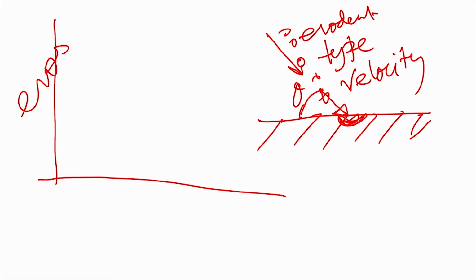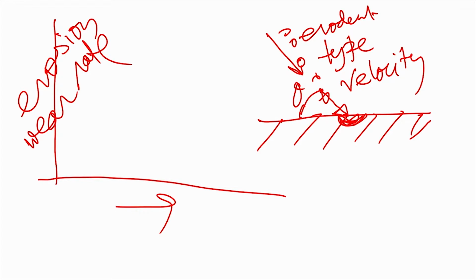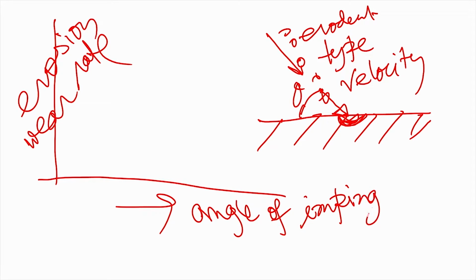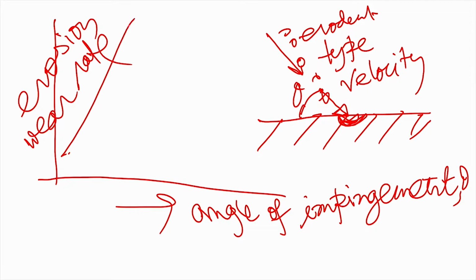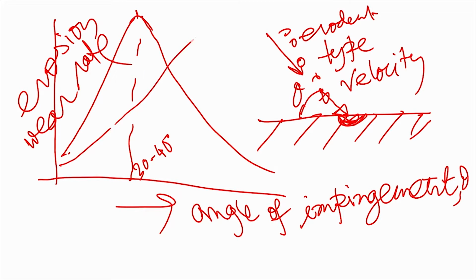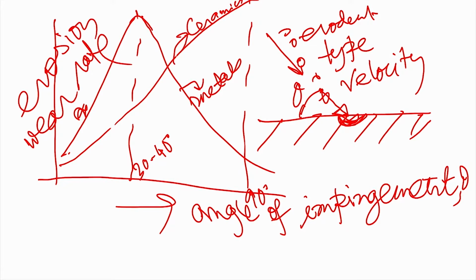Now, if you plot the erosion wear rate as a function of the angle of impingement, that is theta, then in the case of metals, it goes through a transition at around 30 to 40 degree theta values. In the case of ceramics, it goes on increasing up to the angle of 90 degree. This is the case for the metals, and this is the case for the ceramics. So, for ceramics, erosion wear is maximum at 90 degree.